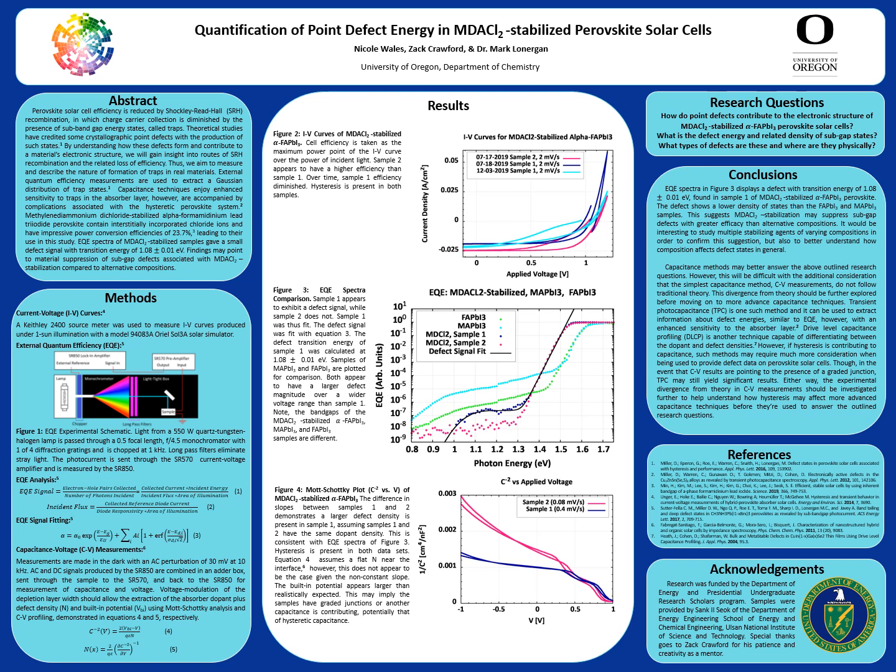Figure 2 demonstrates the IV curves of two different samples of MDA-Cl2 stabilized perovskite. Sample 2 appeared to have a larger power quadrant than sample 1, suggesting it has a higher efficiency. Hysteresis is present in all three samples, where data points do not necessarily overlap when taken in reverse or forward bias. Hysteresis occurs when some aspect of a device's history influences its future behavior. There is a consensus within the field that hysteresis in PSCs is linked to changes in the device's electric field that are caused by ionic movement, which may be driven by applied bias.